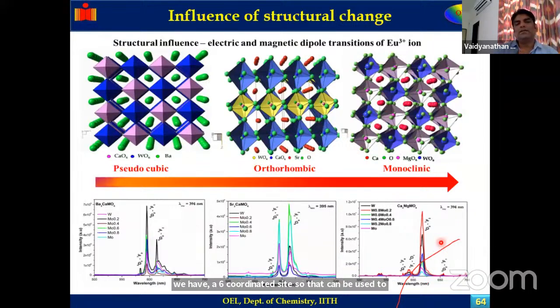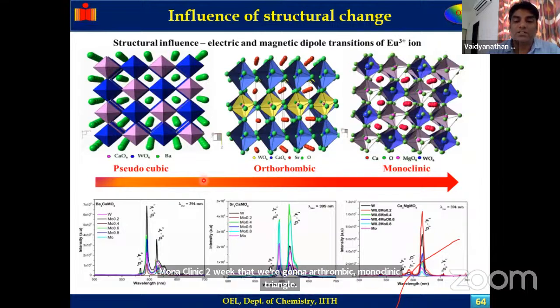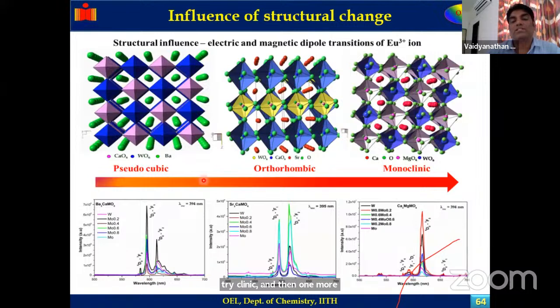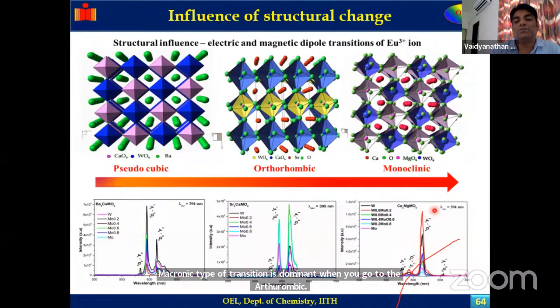Also, one can see that if I have a different structure, there are 7 crystal systems: cubic, tetragonal, orthorhombic, monoclinic, trigonal, triclinic, and then one more is hexagonal. These are the 7 crystal systems. When you change the crystal system, there is also a possibility of changing the emission intensity. For example, in pseudocubic, only the magnetic dipole transition is dominant. When you go to orthorhombic, both emissions are possible. When you go to monoclinic structure, only red emission is possible.